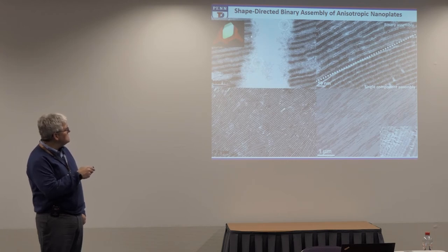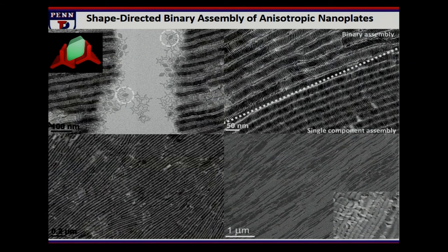But if you do build these, then it will actually organize as I was just illustrating. So here you can see a defect where the system's been pulled apart. And so these arrays sort of flop over, so you can kind of see how they were sitting in the structure. The X-ray is more conclusive in terms of the structure. But this is now the piece of the puzzle with a pretty complex shape, but they've self-organized so that they have complementary components. And so that raises this possibility that you might be able to take two materials that have interesting properties that you can't normally combine, and by engineering their shape, they'll want to get together and to make a very specific crystal structure.